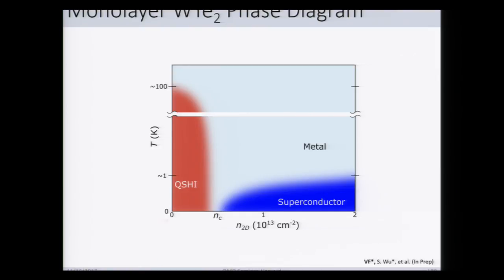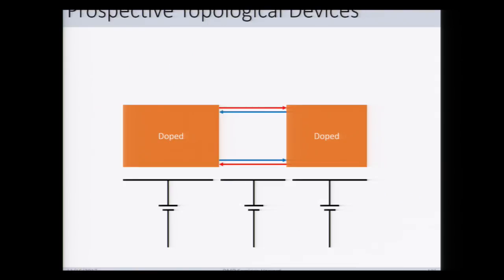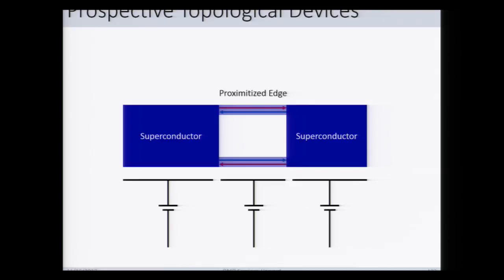And the fact that all of this is accessible within a very low carrier density range allows us to envision new kinds of topological devices within a single homogeneous material without any new materials interfaces. So for example, the same device structure that I showed earlier in the talk, where we have the doped tungsten telluride on either side of the undoped region with the helical edge modes, at lower temperature, we will have superconductivity on either side and hopefully proximitize these edge modes. If this is short enough, we'll hopefully get a Josephson effect.